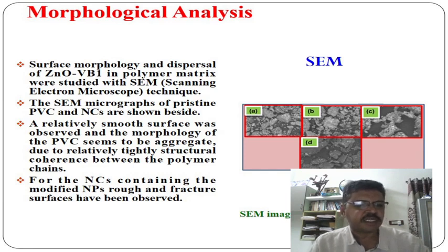For pristine PVC, a relatively smooth surface was observed, and the morphology of the PVC seems to be aggregated due to the relatively tight structural coherence between the polymer chains. However, for the nanocomposites containing the modified nanoparticles, rough and fractured surfaces have been observed. The morphology of pristine polymer and nanocomposites can be attributed to the use of sonication and modifier. The grafting agent caused a positive effect on the dispersion, and finally it has to be noted that the fabrication process, including heating treatment and sonication, directly affects the morphology of the pristine PVC.